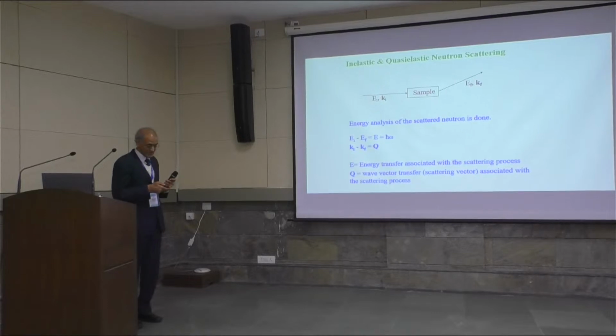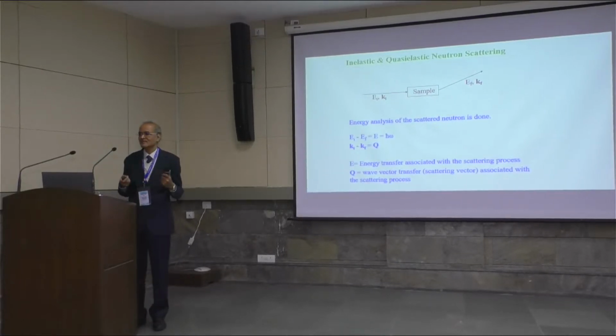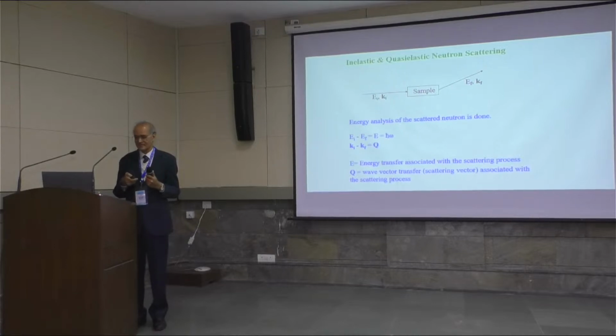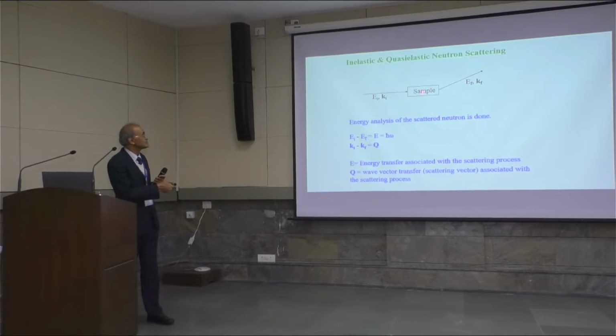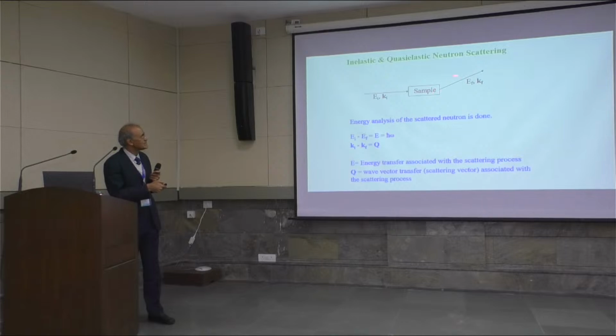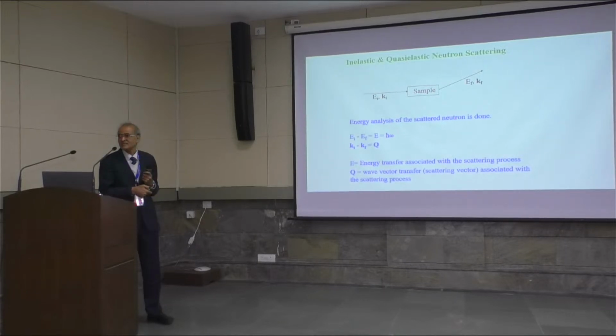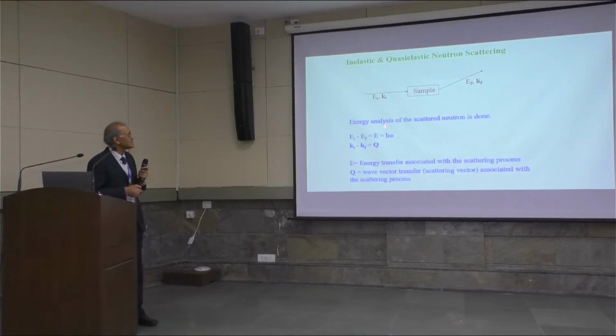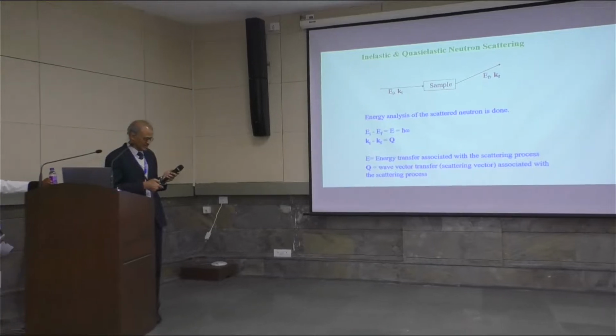To go a little further, neutron scattering is like Raman scattering. Essentially, what happens is you have an incoming radiation, you have a sample, and you have outgoing radiation in different directions, and you look at the energy and momentum conservation. Like in Raman scattering, the radiation energy changes, and the change in energy is related to what excitations we are talking about. Similarly, there is a change in momentum. In diffraction experiments, for example, this is very different. So what you need to really look at is the change in energy and momentum of the neutron radiation, and that allows you to study the dynamics.